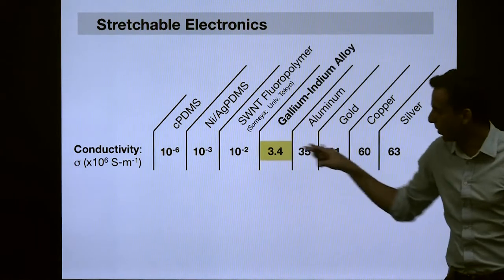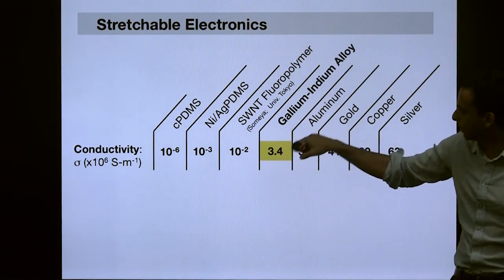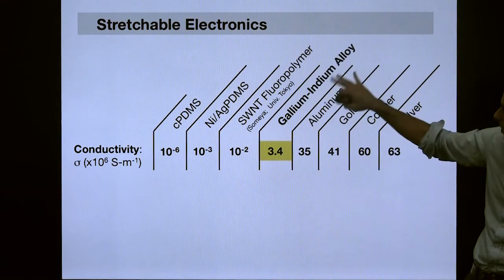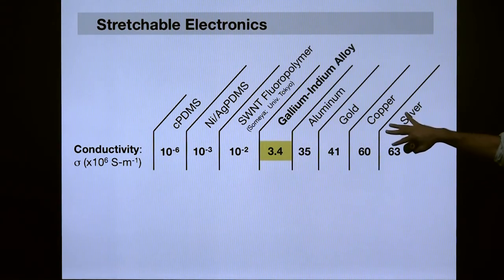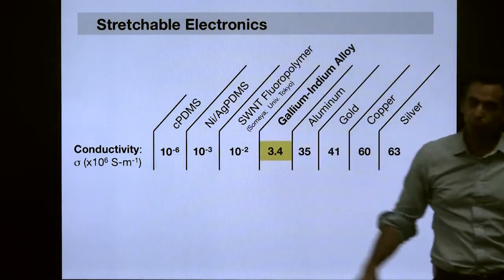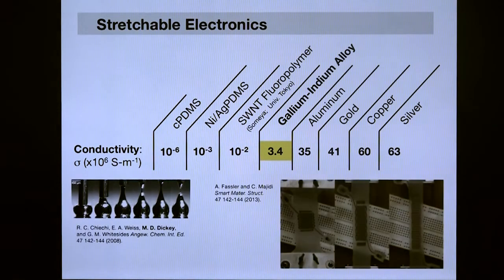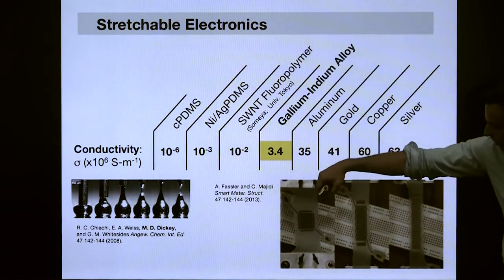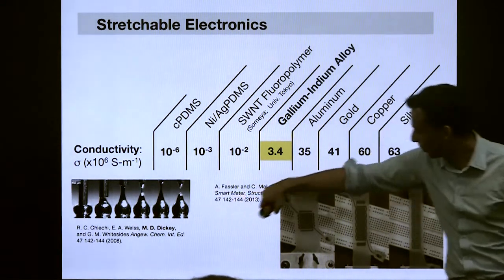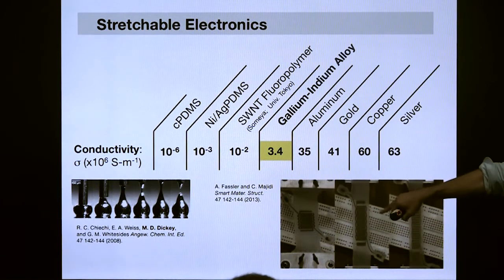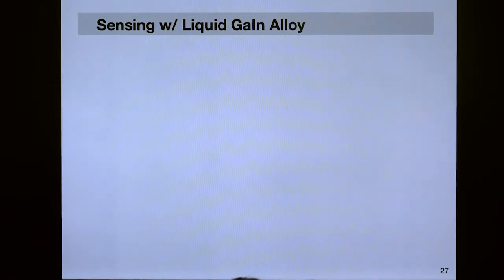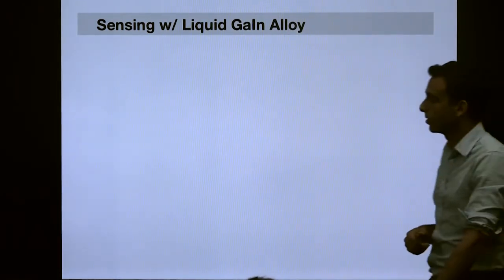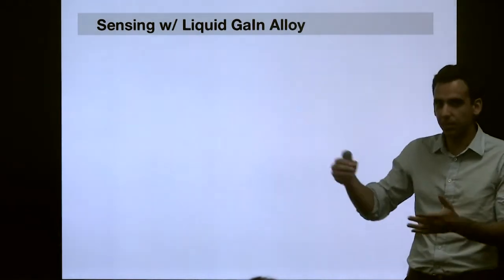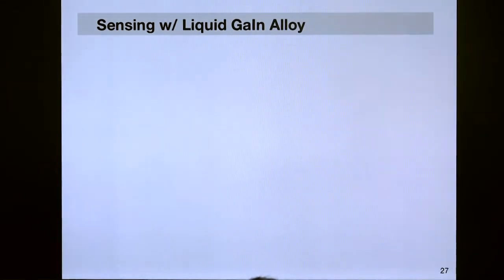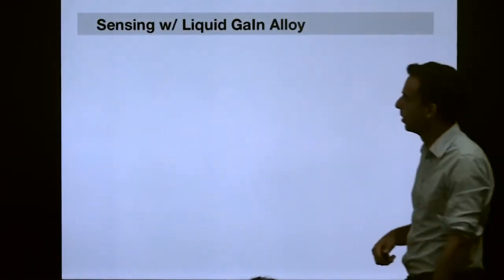In terms of volumetric conductivity, you can see how liquid phase metal alloys like gallium-indium are much closer to conventional metal wiring than they are to conductive elastomers out there. And here's an example of taking a microfluidic channel of this liquid metal alloy and putting it in rubber, and you see that even as you stretch it, the microfluidic channel remains intact. That's great because it's one mode of very highly stretchable circuit wiring. By stretchable, I mean as stretchable as the surrounding rubber. So it could be as much as 5, 10. You could stretch almost to 10 times the natural length of your circuit.